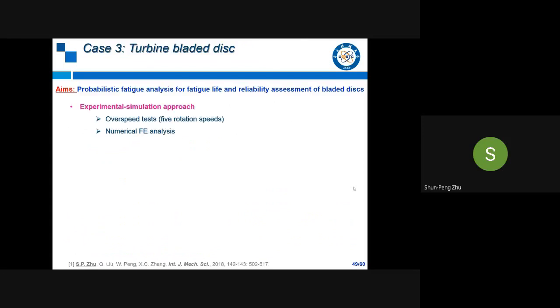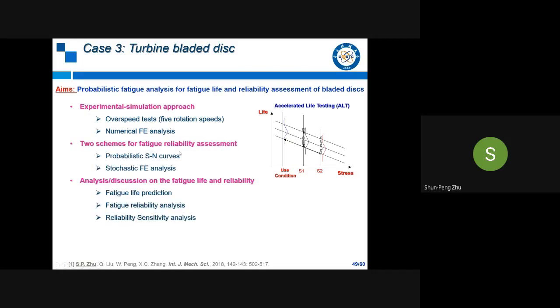The third part is also a turbine-related disk. For this part, we also start from the test and the simulation. The test here is an overspeed test, which is a kind of accelerated life testing, where we test at higher stress and try to extrapolate to the lower, normal use condition. This is just the overspeed rotating test.